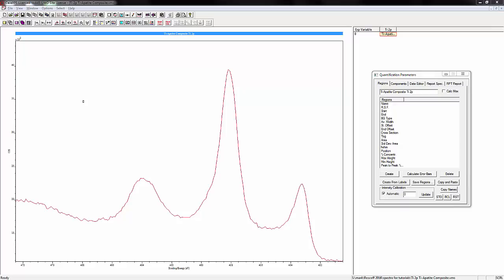For the transition metals, it shows a number of things. We're going to have an asymmetric peak for the metal, we have spin orbit splitting going on, and so we may have to deal with multiplet splitting for some of the states. This sample has already been charge corrected to carbon 1s set to 284.8 eV for adventitious carbon.